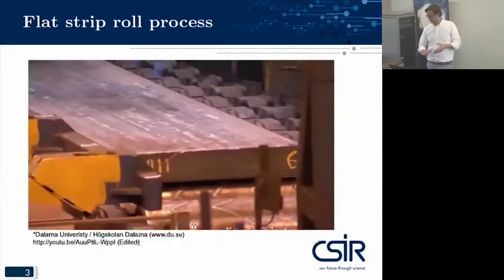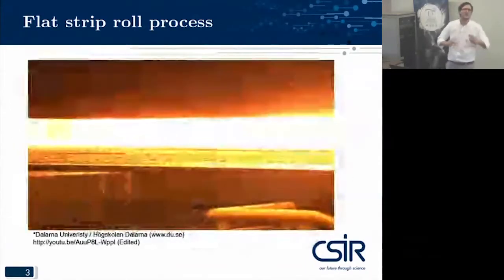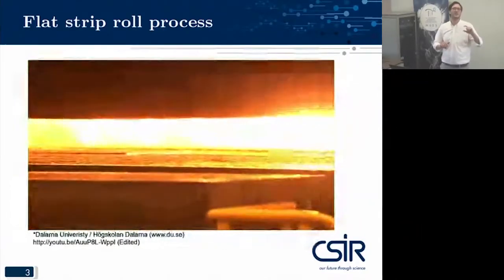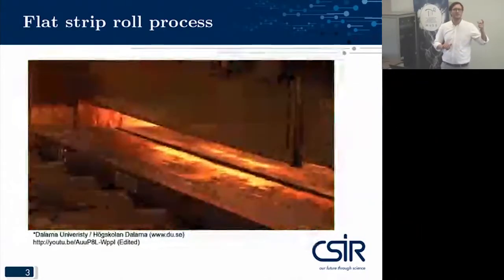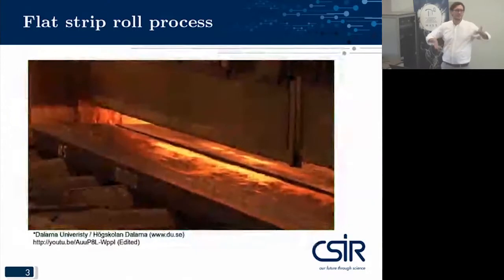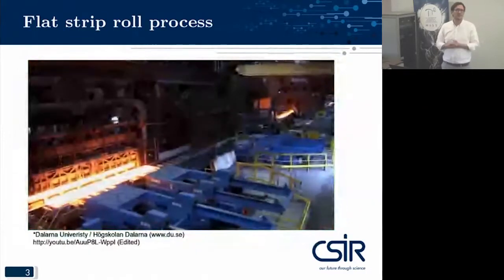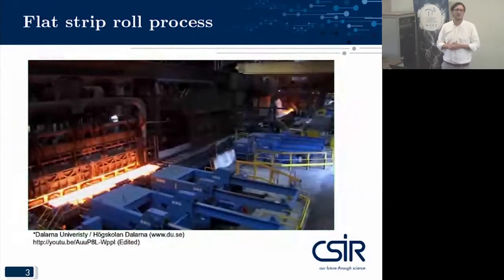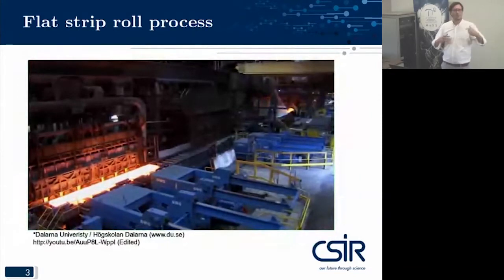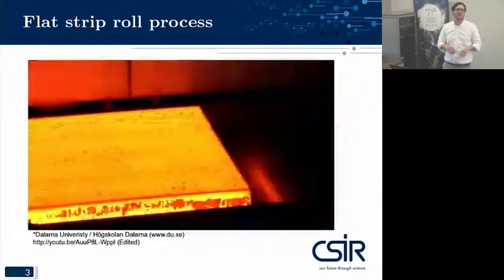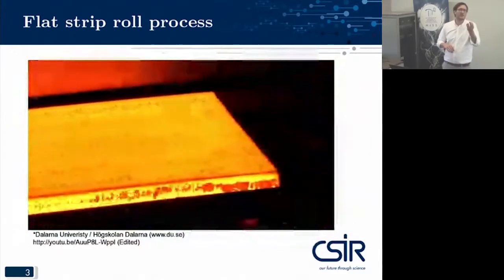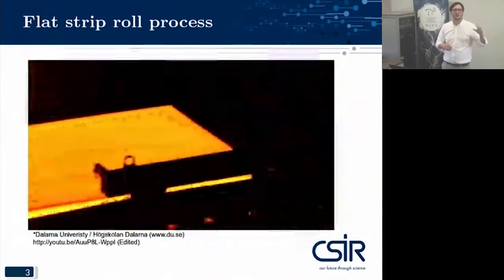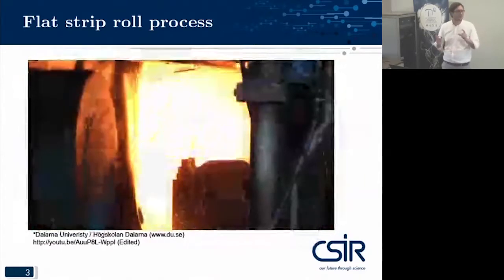Just a quick little video on what this typically is. That is a massive piece of metal. The metal slab is about 20 millimeters thick, and this goes into a furnace, which heats it up. In this specific case, it's a high-strength alloy. It's heated up to around 1,200 degrees Celsius, and then it gets rolled and washed. You'll see very soon, as soon as they move it, there's scale that forms on the surface of the material. This is washed, and then it's rolled through the process.